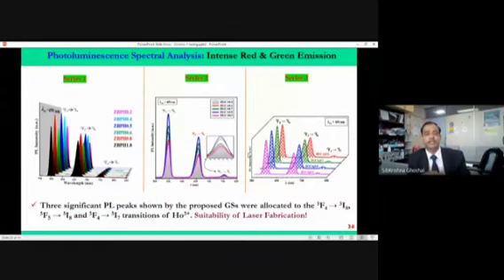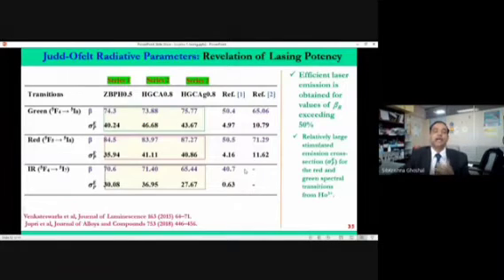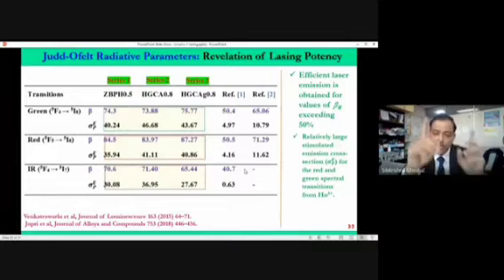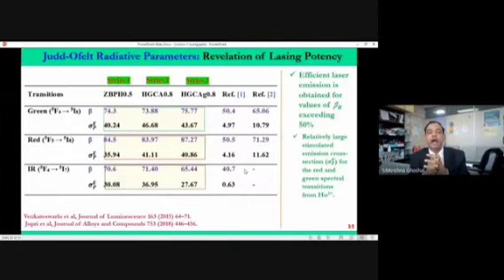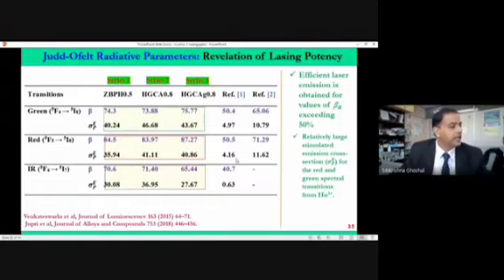Then we look at the photoluminescence, which is the emission spectroscopy. And we see intense red and green emissions. So these materials are really suitable for red and green laser fabrication. And for the first time, you can see the literature and check. For the first time, we show that we can get very high branching ratio and stimulated emission cross-section in this material, and that's why our aim is fulfilled. So the stimulated emission cross-section and the branching ratio of this material is very high, and that's what we wanted to achieve, and this is the right material for fabricating the laser.